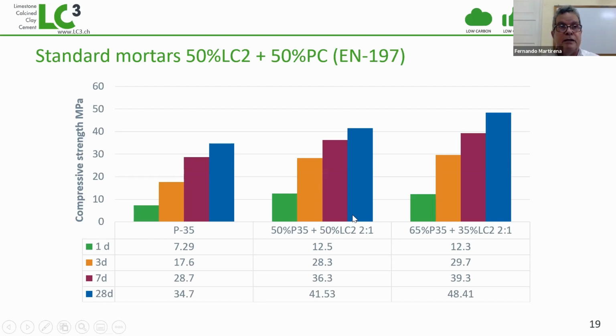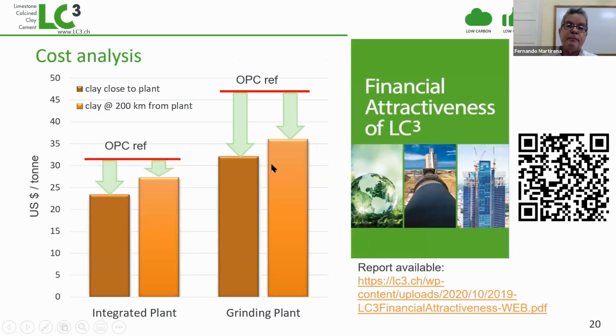So you're having a material where you're replacing half of the Portland cement and you're not compromising the strength, but increasing the strength. And also you realize here that if you try to increase the amount of Portland cement, I mean, you have some minor contribution to the strength. So it's not a big deal.